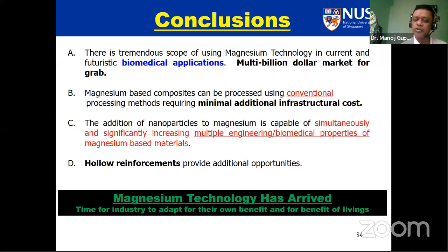The second thing, very important from the industry point of view, is that we can use conventional methods. We don't have to invest a lot of money - you can easily buy very simple furnaces and do the needful. Number three, if you want to go into composite technology, don't go for micron size particles, go for nano size particles. Because by putting a very small amount - if you use micron size, you have to put 20%, 30%; if you use nanoparticles, you're only putting in not more than 3 weight%. The best results, like the ones I've shown you, come around 0.5 and 1% volume percentage, which translates to a maximum of 2.5% by weight, depending on the type of reinforcement. And they can do an amazing job improving the properties of magnesium.